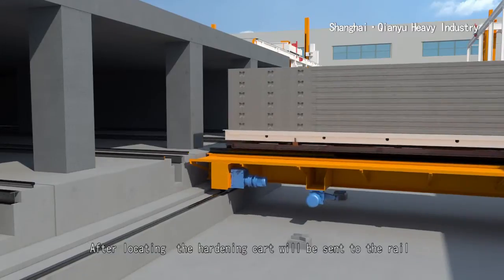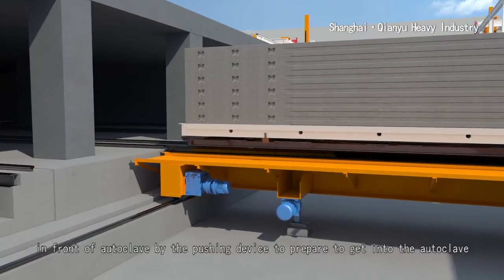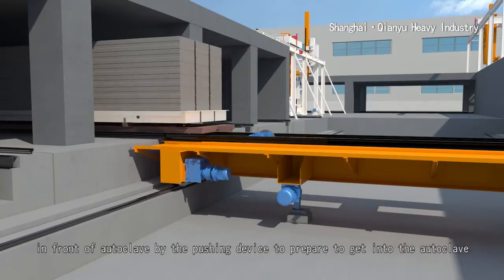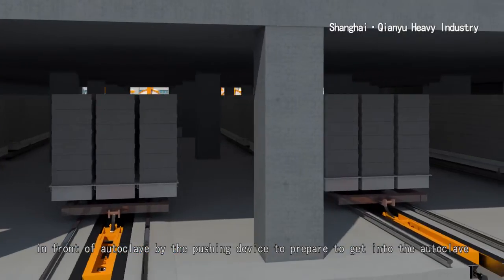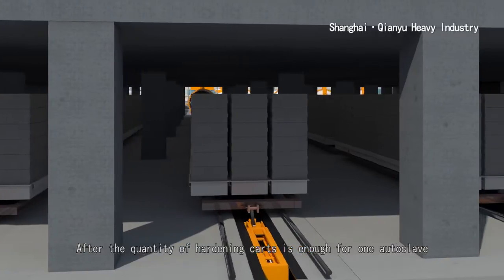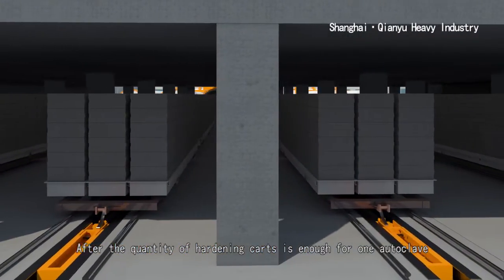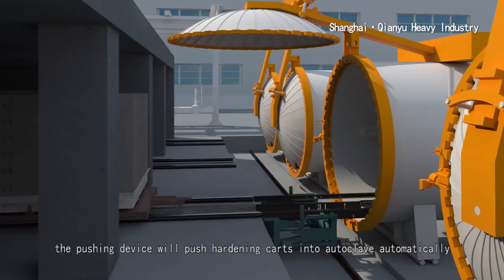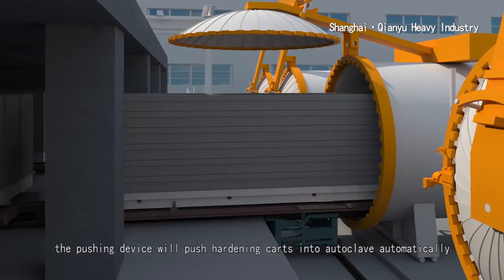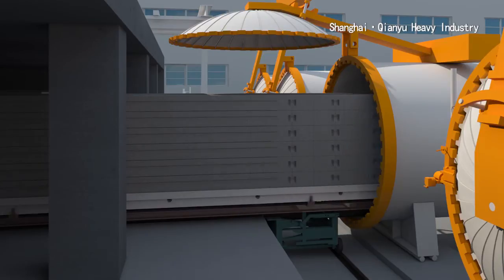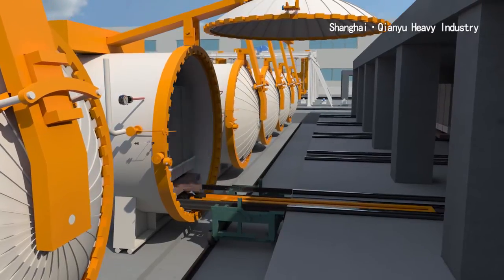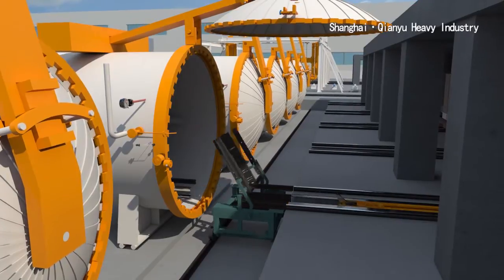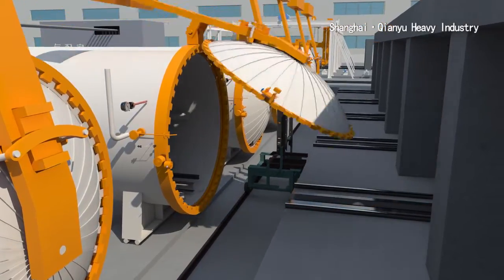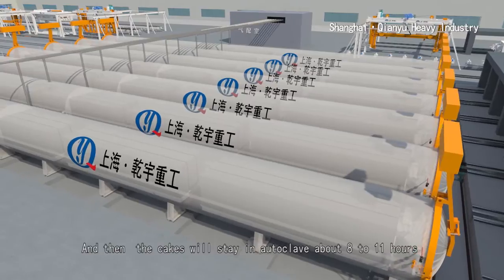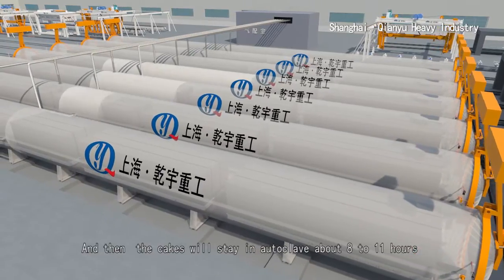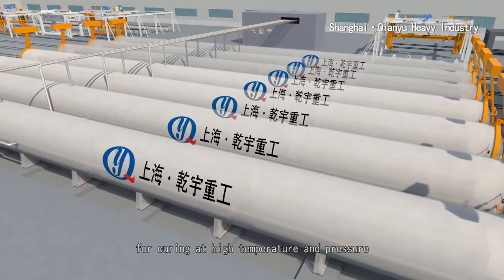After locating, the hardening cart will be sent to the rail in front of autoclave by the pushing device to prepare to get into the autoclave. After the quantity of hardening carts is enough for one autoclave, the pushing device will push hardening carts into autoclave automatically. And then, the cakes will stay in autoclave about 8 to 11 hours for curing at high temperature and pressure.